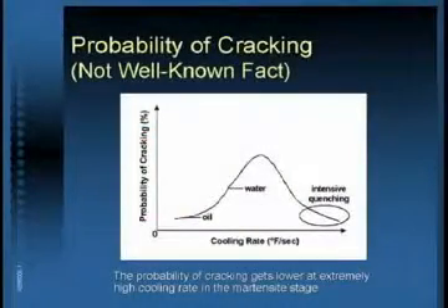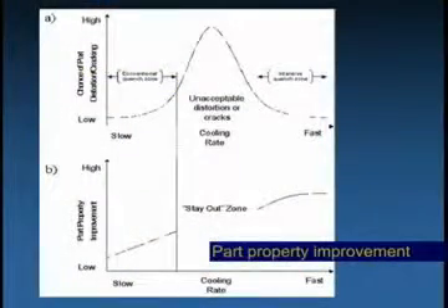In the intensive quenching zone, very high cooling rates reduce part distortion and probability of cracking and at the same time provide superior part mechanical properties. With intensive quenching techniques, the heat treater can have both, better part properties and lower part distortion. Have your cake and eat it too.